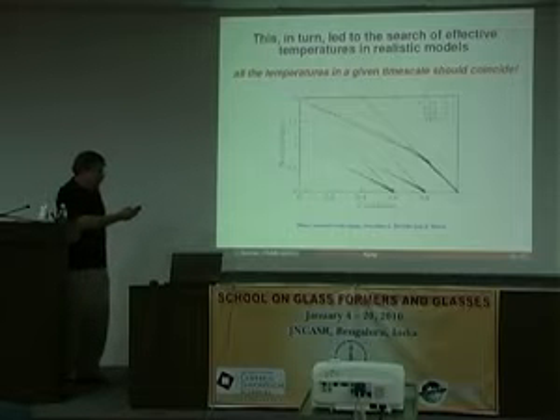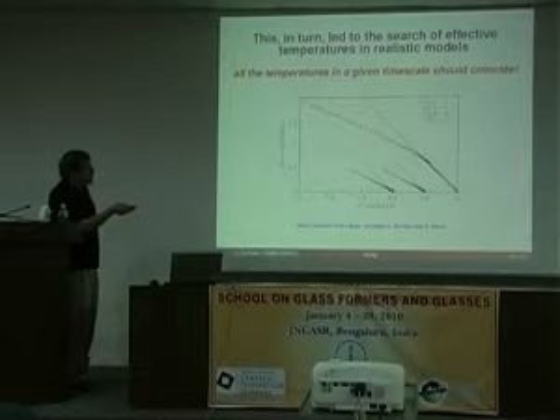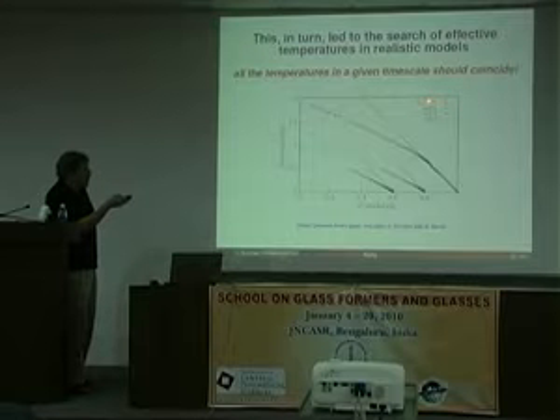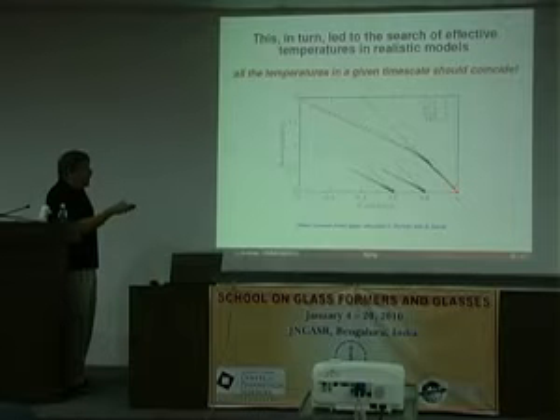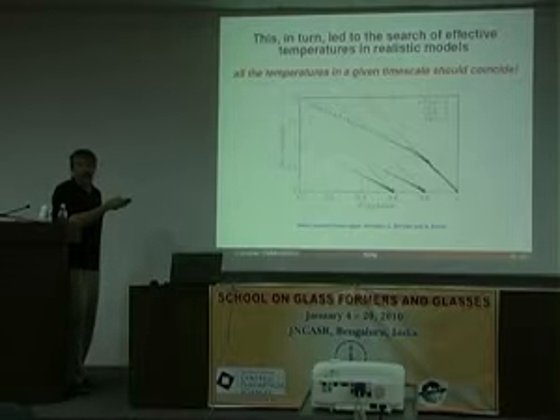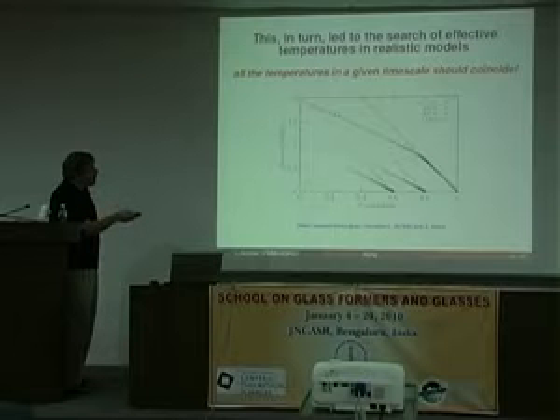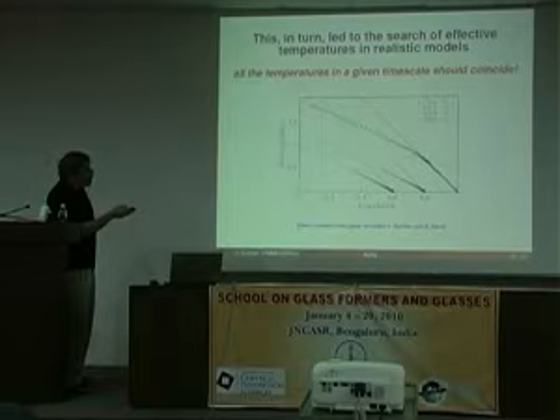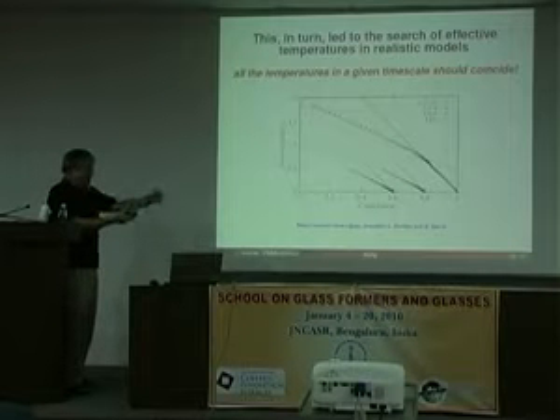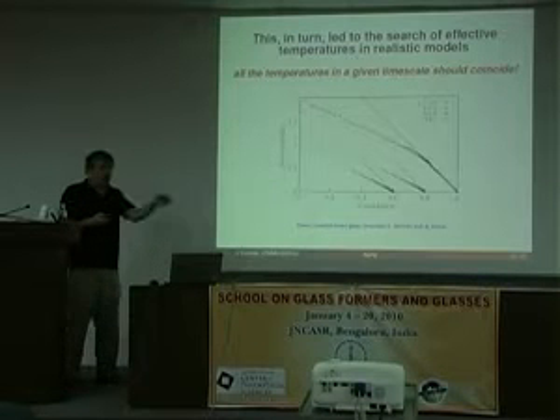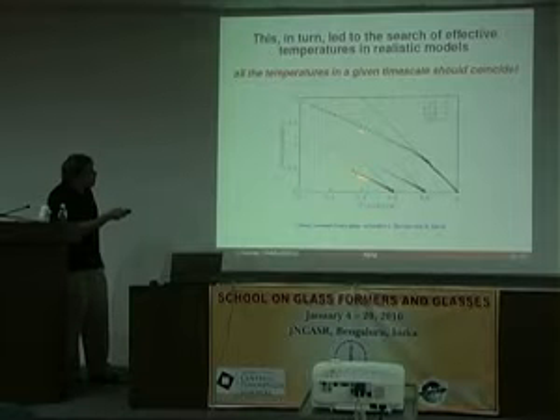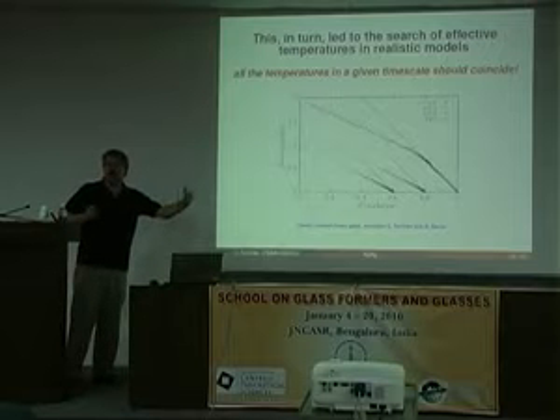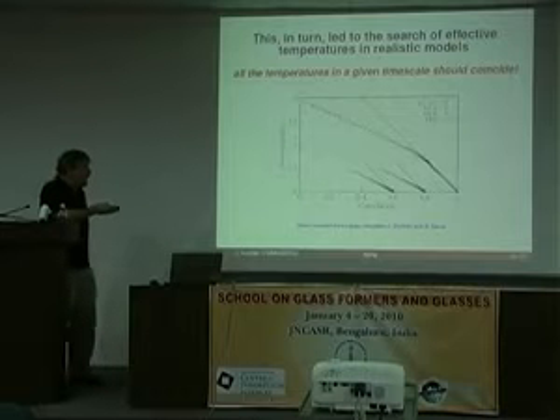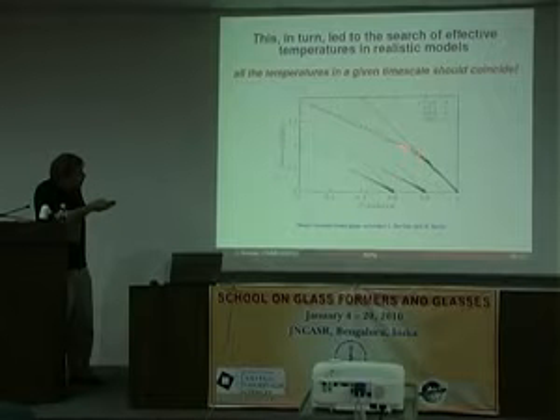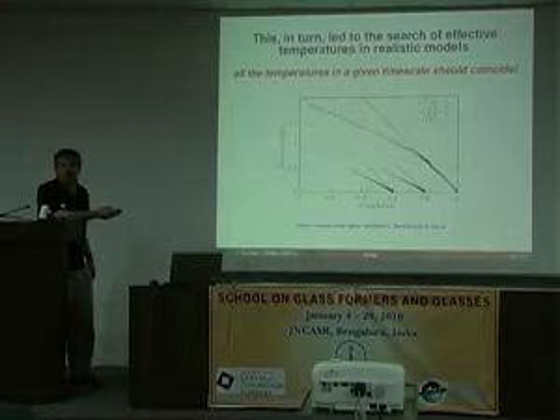And this is taken from an article of these gentlemen. And what you see is that, for example, for rho k, where k is the density modulation at this k, you get something like this. They did it for many k. I didn't put it for clarity of presentation, but you get the same kind of broken curve with parallel lines. But I thought it was nicer to put the self-diffusion. This is a binary mixture, so you can do the self-diffusion of the big particles and of the small particles, and you get lines that are very well parallel to this one. So you don't get this straight, because this is a long distance thing, so you don't see the rapid vibrations in this plot.